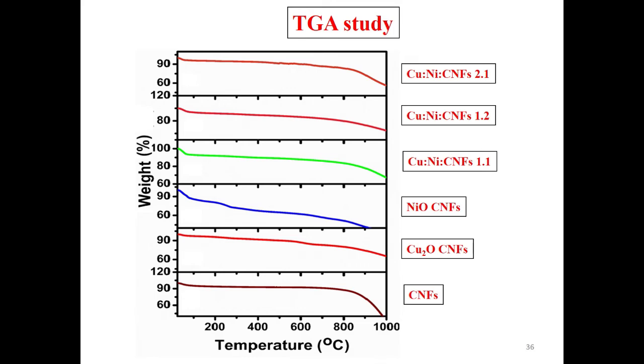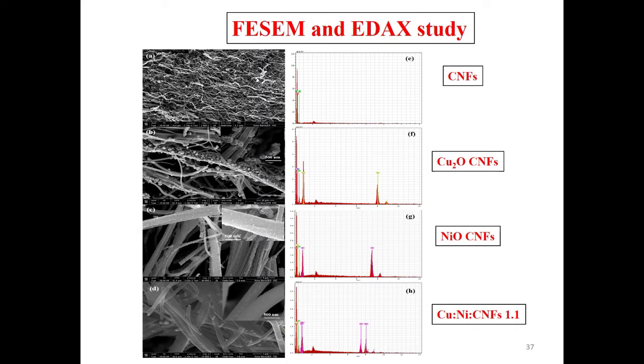This is the TGA study, and 2:1, 1:2, and 1:1 are found to be thermally more stable as compared to nickel oxide, cuprous oxide carbon nanofiber, and simple carbon fibers. FESEM and EDAX study. Here the morphology study shows the decoration of copper nickel nanofiber uniformly dispersed over the carbon nanofiber, and a very fine and interesting morphology is observed in this particular pair.